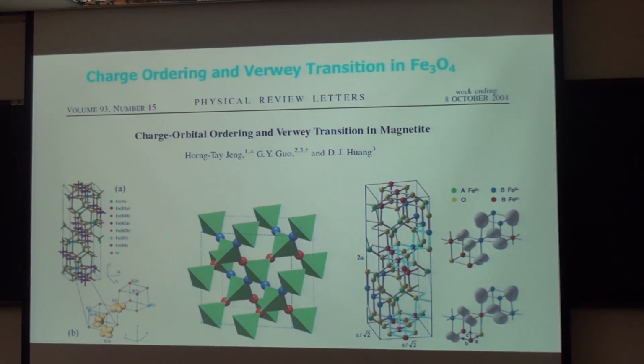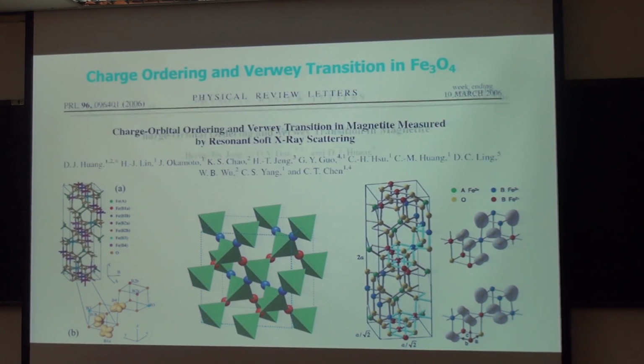Another interesting material is magnetite. The reason is similar to chromium dioxide. When I was a postdoc in National Taiwan University, Professor Guo and his collaborators made a very important finding, that is the charge orbital ordering and the Verwey transition. For the first time, they explained the Verwey transition as a consequence of the charge orbital ordering. And later, experimentally, they observed such charge orbital ordering.